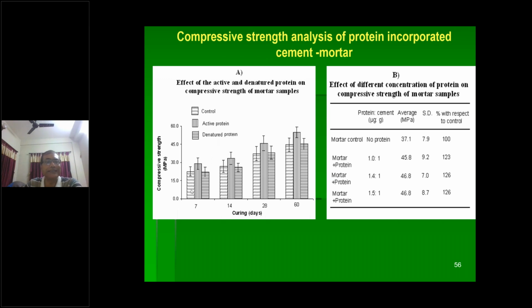What we have written in this case is that as we increase the curing days, the addition of active protein gives an improvement in strength compared to the control and also the denatured protein. Also, if we increase the protein concentration, in these proportions, we get an increase in average strength. In this range we get high improvement, almost 23 to 26% with respect to the control.